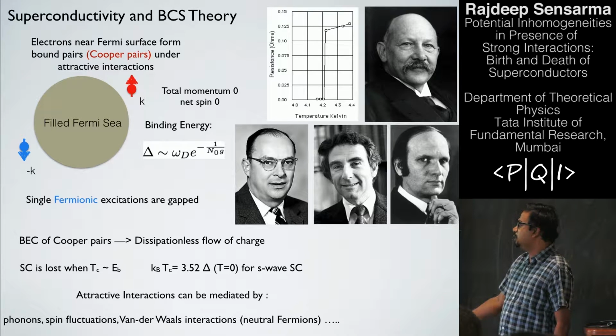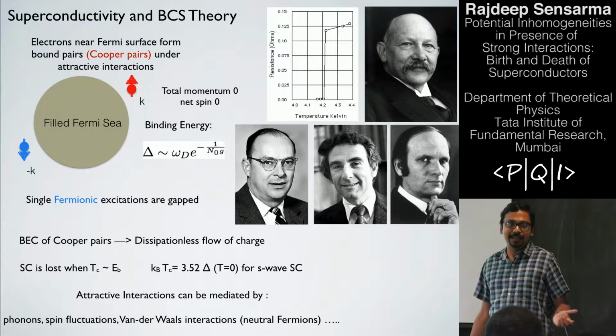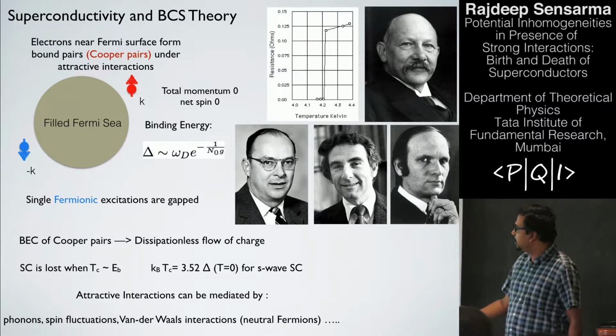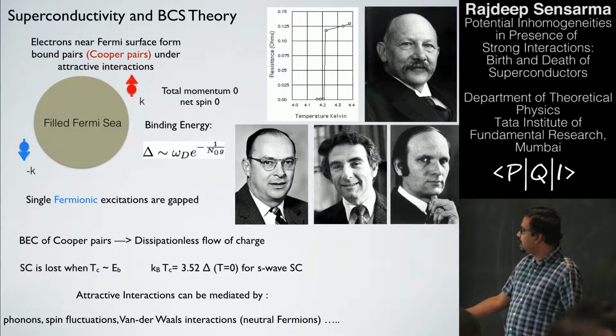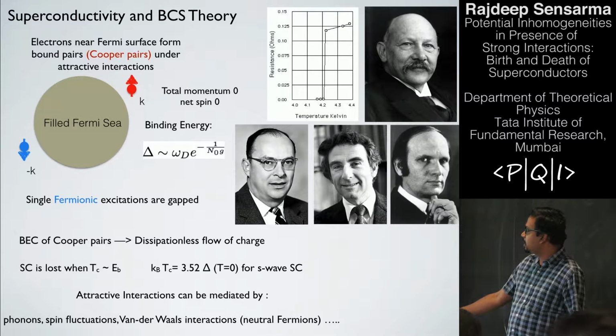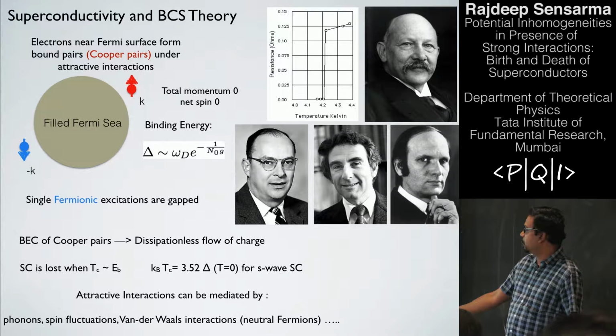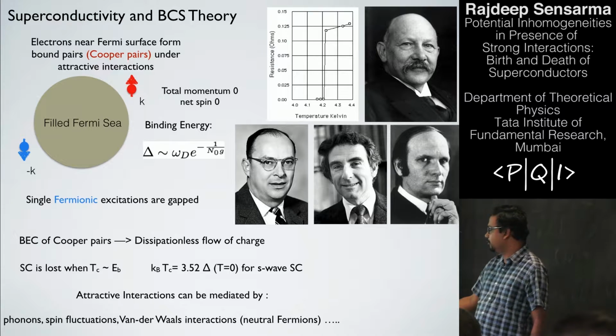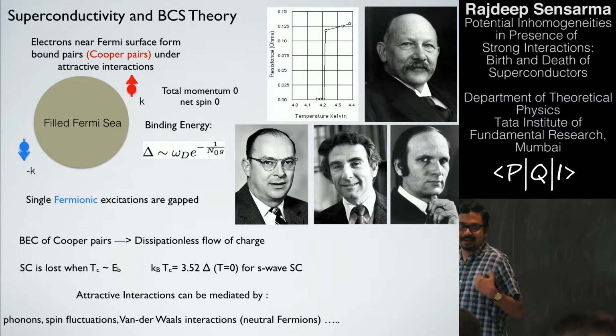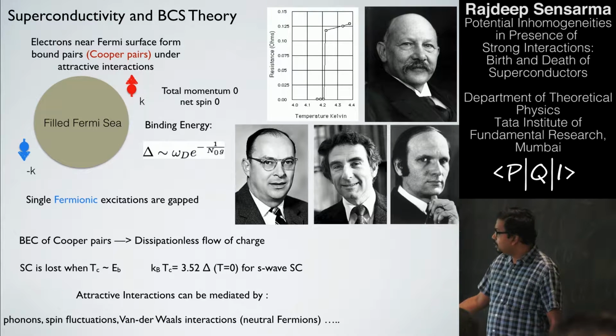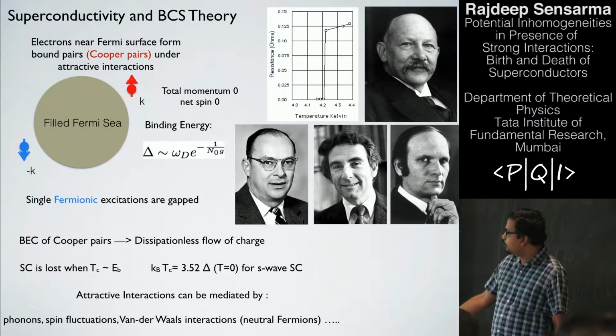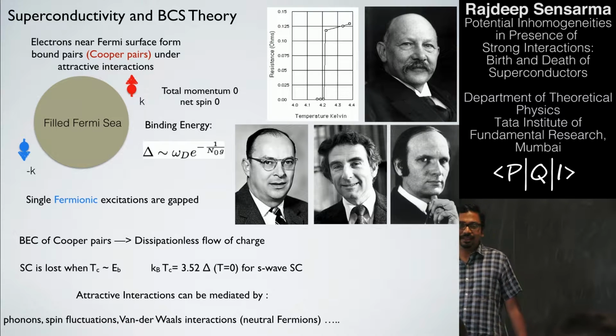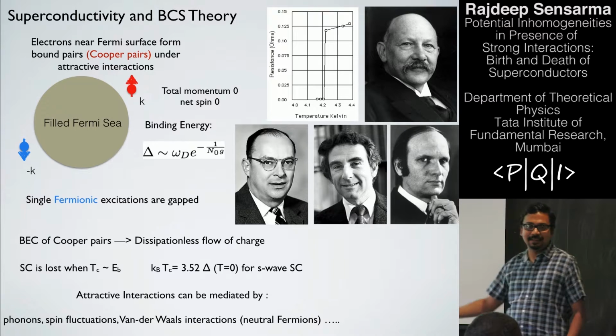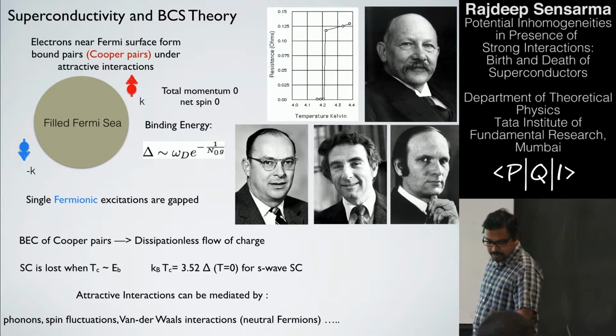So, a couple of things came out of this theory. For example, superconductivity is lost when you have raised the temperature to the order of the binding energy, when bound Cooper pairs lose their meaning, which also means that Tc is related to the single particle fermionic gap at zero temperature, at least for an S-wave superconductor. There is a particular number, 3.52, etc. Now I started by saying that there are attractive interactions between electrons. This can come due to various reasons. This could be phonons, this could be spin fluctuations. If you have cold atoms, this could be Van der Waals interactions, and so on and so forth. But as long as you have an attractive interaction, the BCS theory tells you what is going to happen.